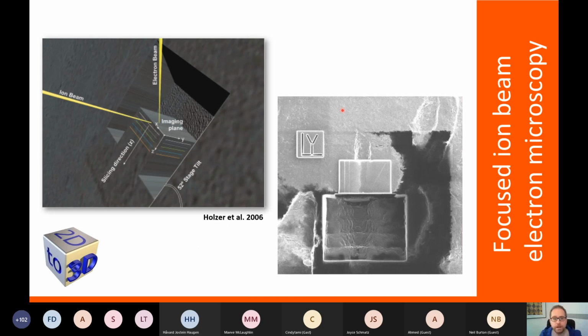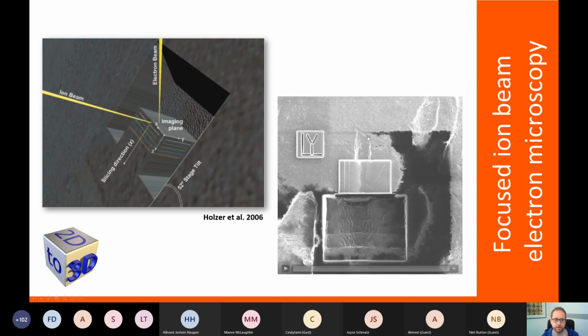But you can not only do one cut, you can also do a sequential slicing of your sample. And you must imagine this similar to a salami, where you start slicing the salami up, but every salami slice is maybe only of the order of 5 to 10 nanometers in thickness. And then we have the ion beam cutting the sample and the electron beam imaging each slice sequentially. So here on the right-hand side, you will see a little video of how this works, looking down the ion beam column. So we're looking down this line here onto the sample.